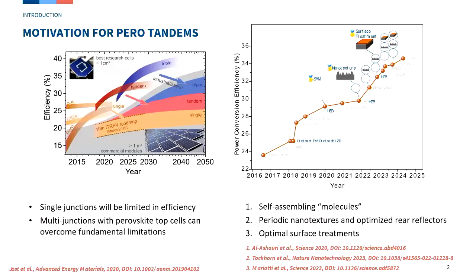And then of course, if you industrialize this technology, then we have modules out there, which we have by today. On the very right side, you see a figure that summarizes the efficiency increase over time for perovskite on silicon. By today, we know that the best cells are about 35% efficient, but 5 years back, there was a strong race, and it was very important to show that efficiency improvement for the technology drive. And we are happy to have also taken part in that race. So we had 3 different independently certified world records in our center in my team.